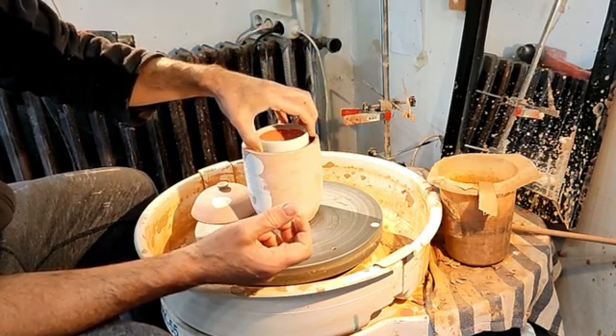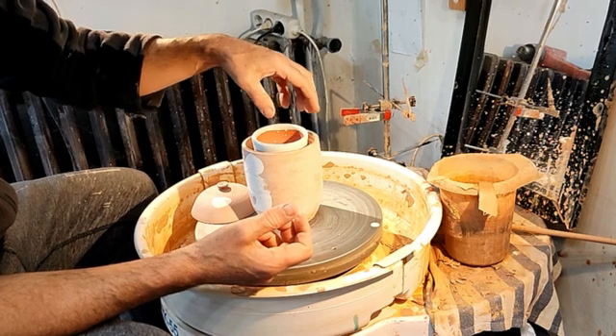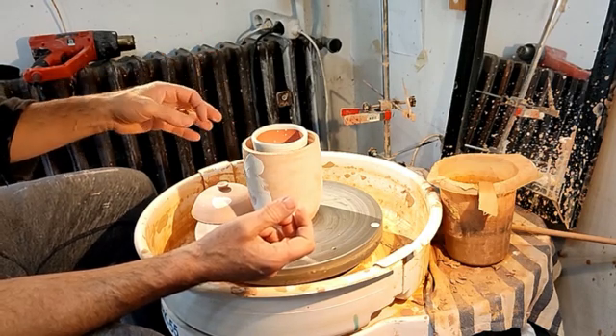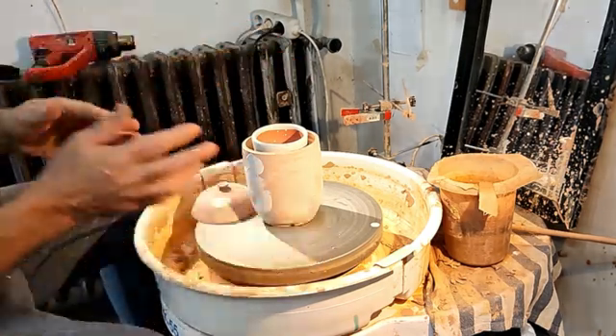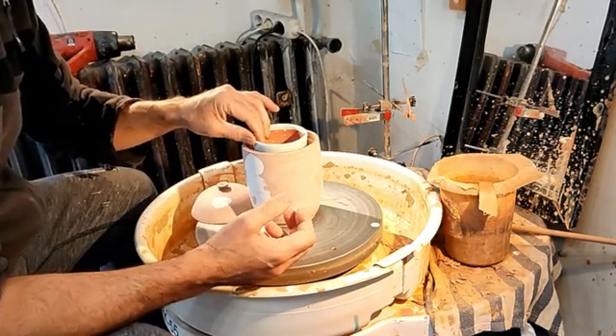If this fails and it gets oxidized, then the copper on the outside might be very light green. And if it fails to get reduction it doesn't look like much of anything — maybe whitish. The inside will be kind of white with a slight tan colour because of the iron, about 1% iron.